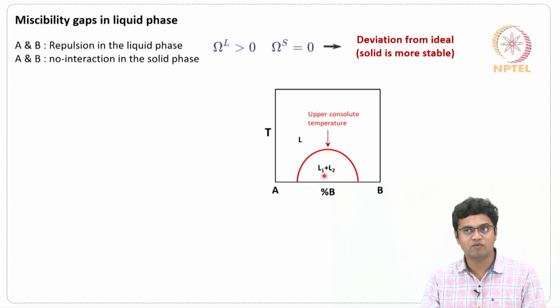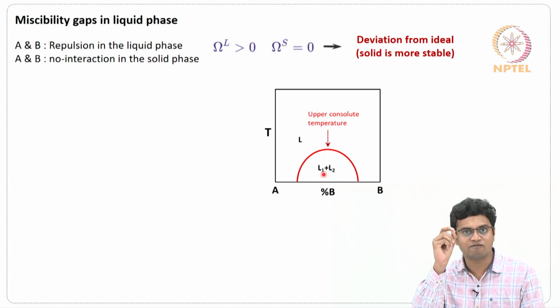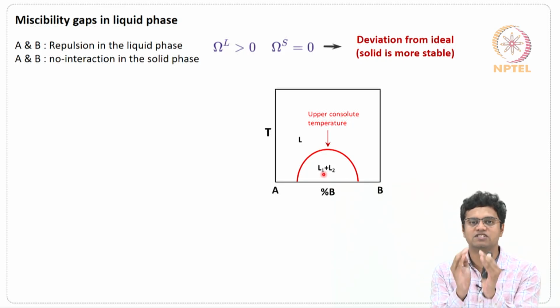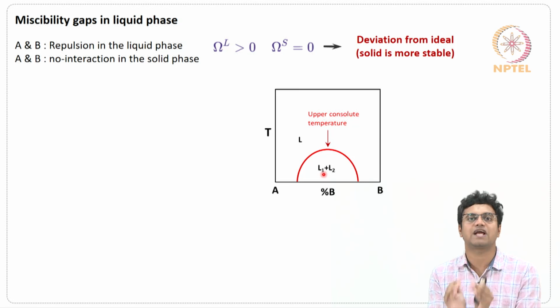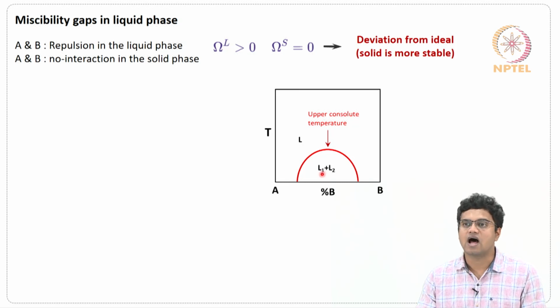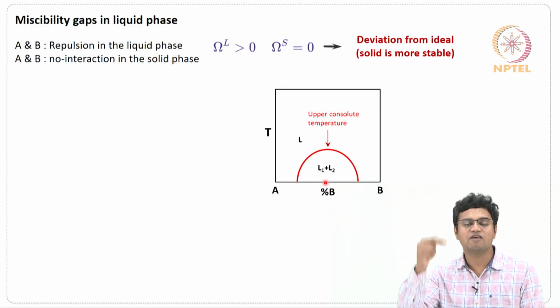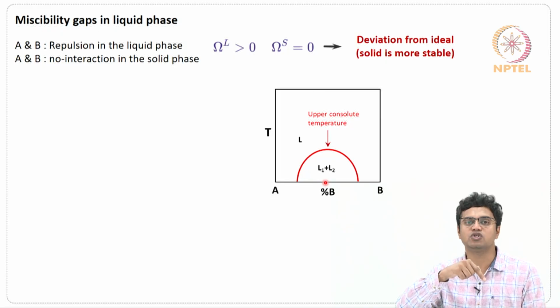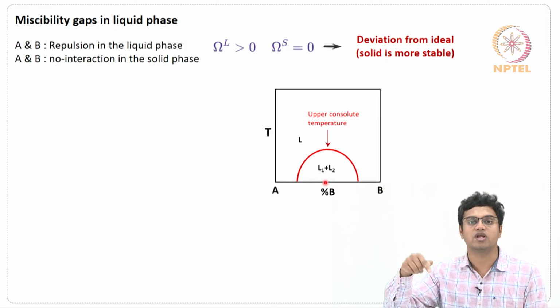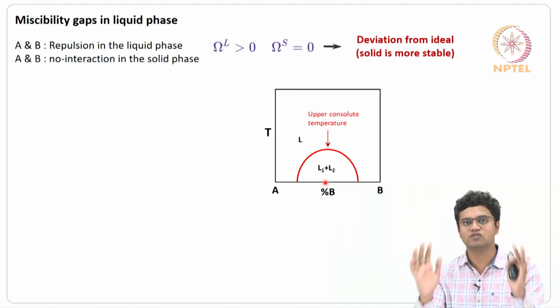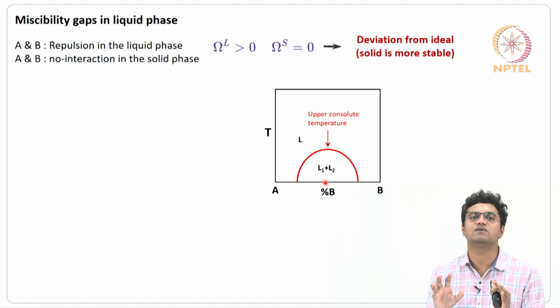The distinction between these two needs to be defined based on the fundamental definition of phase. What is the fundamental definition of phase? Physically distinct, chemically homogeneous and mechanically separable. Now, are these physically distinct? Yes, they are physically distinct. Why? Because they have different compositions. Since they have different compositions, there exists a boundary. Don't think of it like an oil-water system. It's not an oil-water system. Everything is oil. Only the compositional gradient is there.